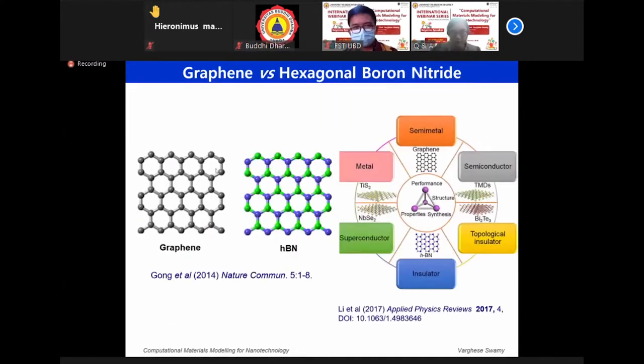So let's start with graphene and HBN. Graphene is shown here. This is a hexagonal lattice, single atom layer structure. The gray balls are carbon atoms. And HBN, the hexagonal boron nitride, is essentially isostructural. Instead of carbon, we have alternating boron and nitrogen here. If you look at the electronic properties, graphene is a semi-metal, whereas HBN is an insulator. That means that these two are complementary materials.